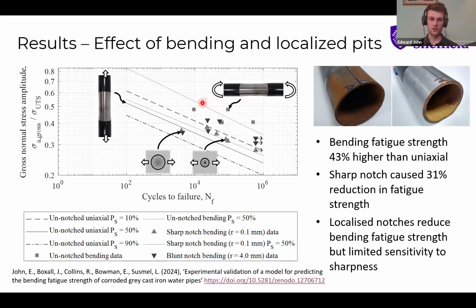So then we added the localized pits that I showed a few slides earlier to some of the pipes, and then did some more bending tests. So this was looking at the dish-shaped one and then the small circular pointy one. So what we found is that these pits did cause a noticeable reduction in the fatigue strength of the pipes. So localized pits do cause damage. But the interesting thing here is that there wasn't really much of a difference between the two shapes of pits. So the upward pointing triangles are the sharp pits, and the downward pointing ones are the blunt ones. So very similar behavior for the two.